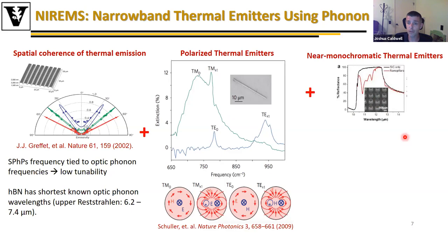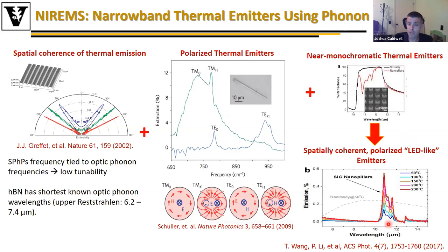And then later on, in collaboration with Thomas Taubner, my group was able to demonstrate very narrow band thermal emitters, as narrow as about 3 wave numbers, whereby heating this up as a function of temperature, you can induce these narrow resonances that can give rise to amplitude dependent modes that are not spectrally shifting with temperature very much. So by increasing the temperature at which you're operating, you can get this narrow band emission stronger and stronger using this thermal emission concept, right?